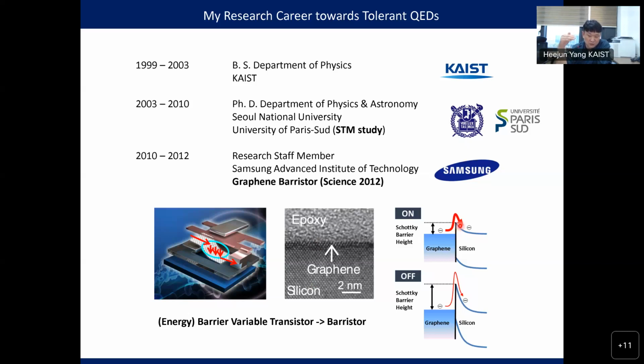accumulate electrons or holes in the graphene, we can shift up or shift down the Fermi level of the graphene, which means we can make a smaller Schottky barrier height and a larger Schottky barrier height, which can be used as on and off. Graphene doesn't have a band gap, but it's a sort of barrier variable transistor, so we name it barristor. But I will not go deeply into this topic today.